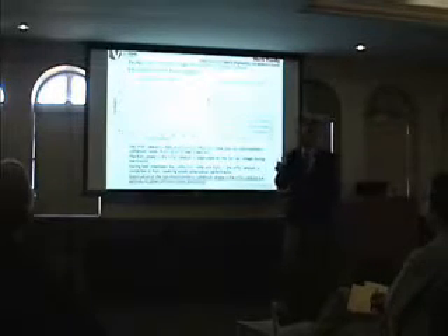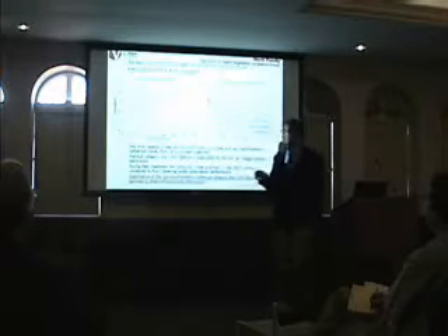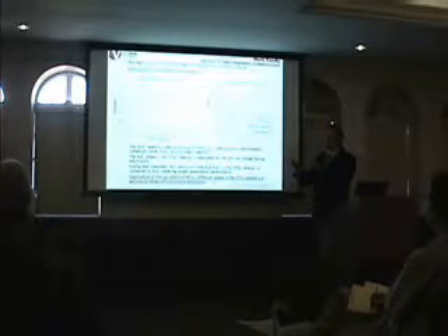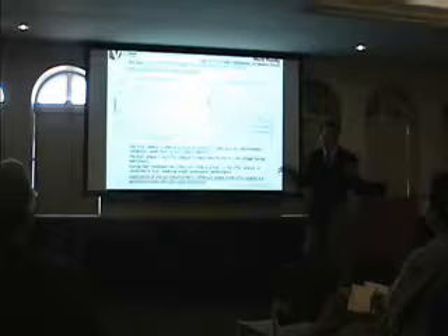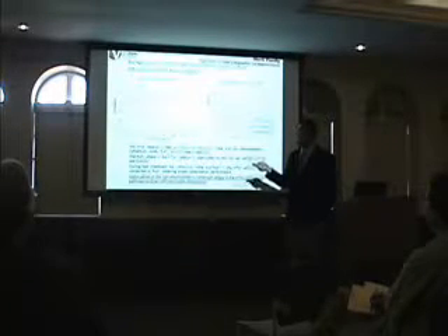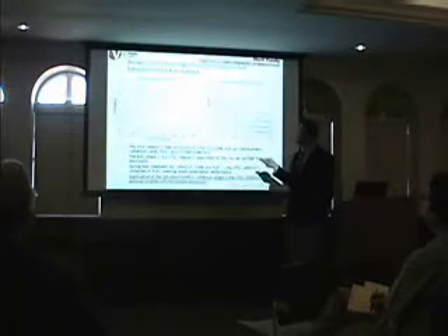Remember, we were trying to make a ruthenium oxide because we knew ruthenium metal wasn't a very good oxygen evolution catalyst. This further perplexed us, and we were saying, my gosh, here we have this metal that we know is not good, but yet it's doing better than even the best stuff that was known.